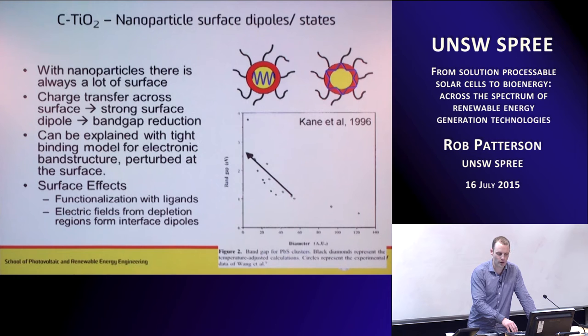Here's the experimental trend for small nanoparticles. The bandgap tends to rise and then sort of saturate, whereas the theoretical prediction looks more like this. It's much steeper. And so you can imagine this having something to do with the surface dipole. So the fact that the surface ends up dominating the physics of the nanoparticle.